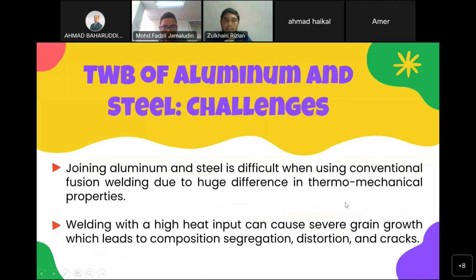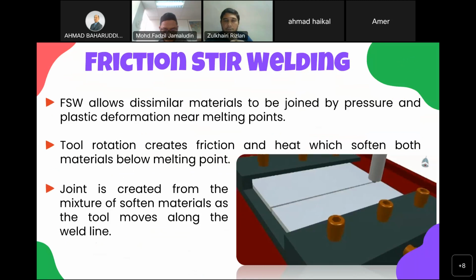So the challenge in the tailor blank of aluminum and steel is the difficulty to join when using conventional fusion welding due to the huge difference in thermomechanical properties. And welding with high heat input can cause severe grain growth, which will result in problems such as composition segregation, distortion, and cracks. So this is where friction stir welding came in handy.